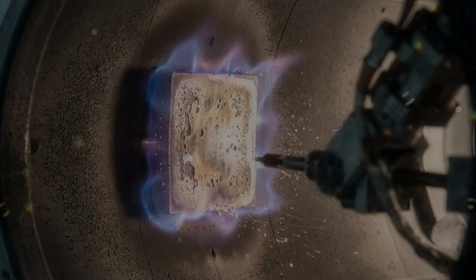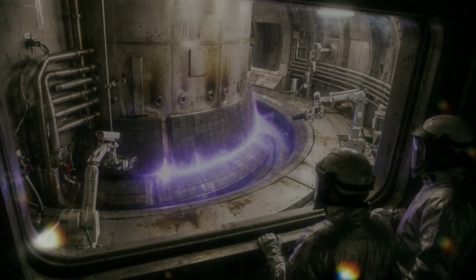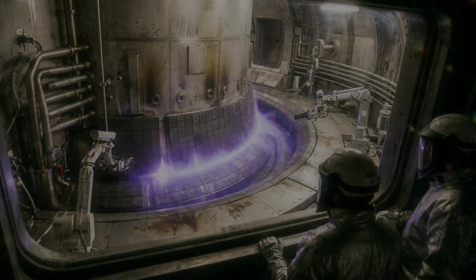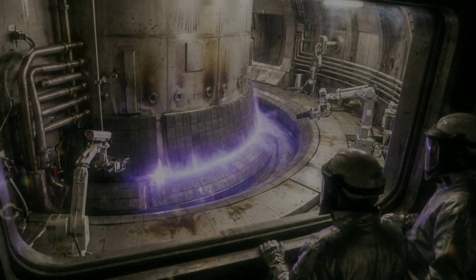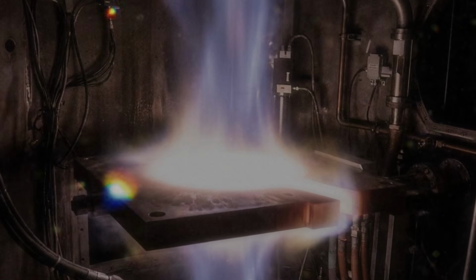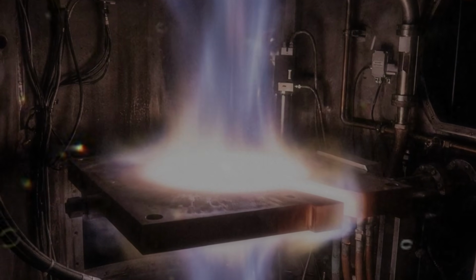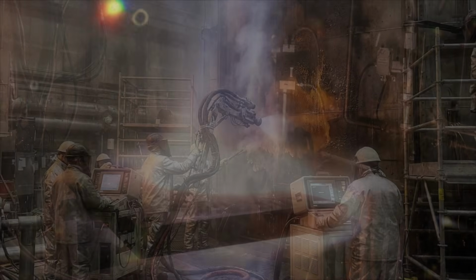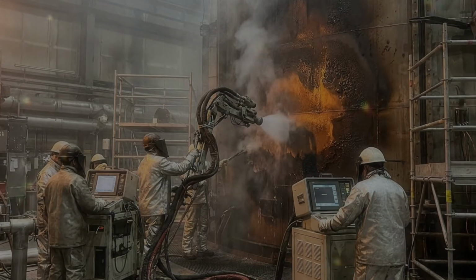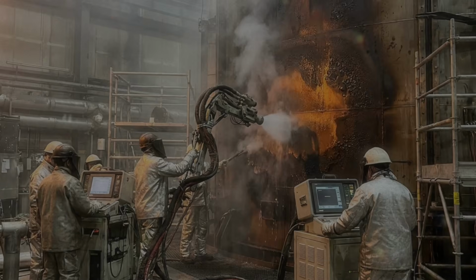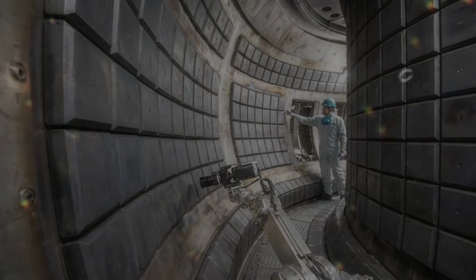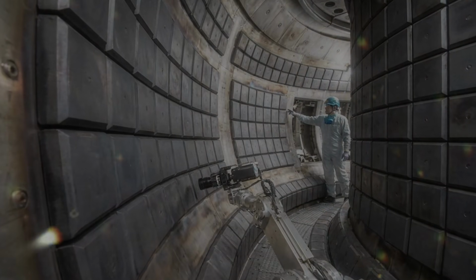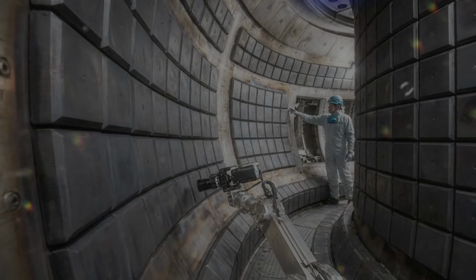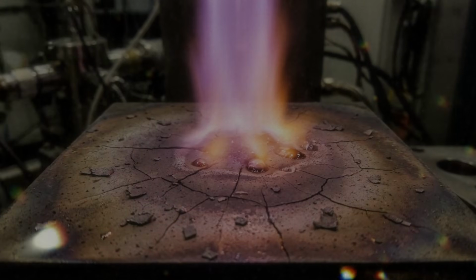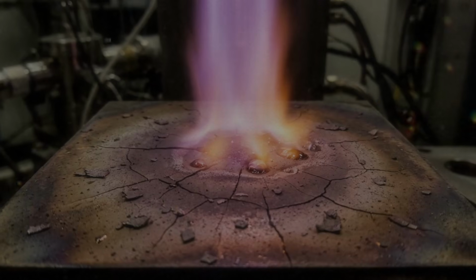There are also questions about fuel retention. Boron-rich films can trap hydrogen isotopes under some conditions. If those isotopes include tritium, that matters. Tritium is valuable, radioactive, and must be carefully accounted for. A coating that improves plasma behavior but stores too much fuel could create another problem. As always, fusion refuses to hand over a free advantage. You solve one difficulty, and another one quietly takes a seat nearby. Still, boron remains attractive because it can make a plasma behave better. In fusion, that is not a small gift.